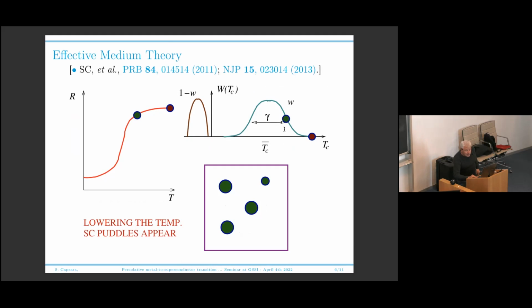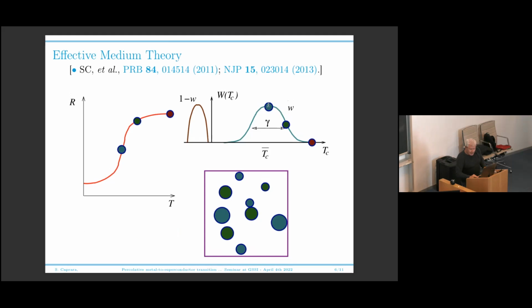Here, there are some islands whose superconducting critical temperature is larger than this temperature. And so you will start to nucleate some superconducting islands inside your system. And then because of these islands inside your system, your resistance will be smaller than the resistance in the metallic state. Because locally, you have zero resistance islands that reduce the overall resistance of the sample. You lower even more the temperature. Now you are here. So all these regions with a superconducting critical temperature larger than this value have turned superconducting. So you have more superconducting regions and you are here in the resistance curve.